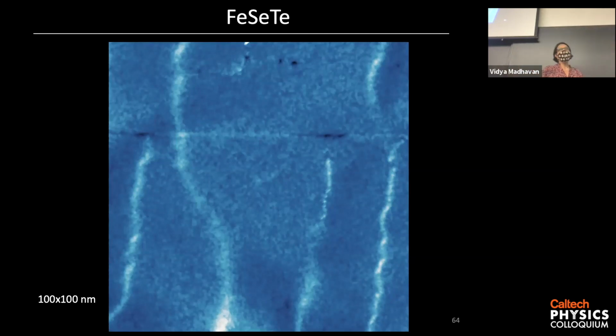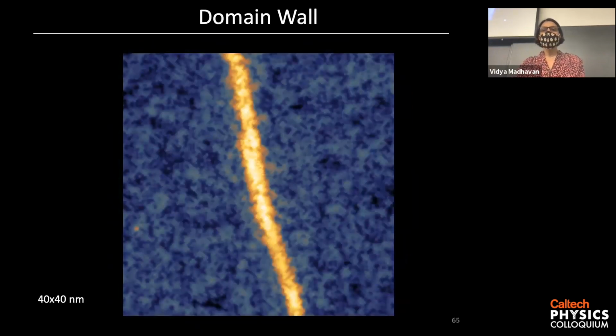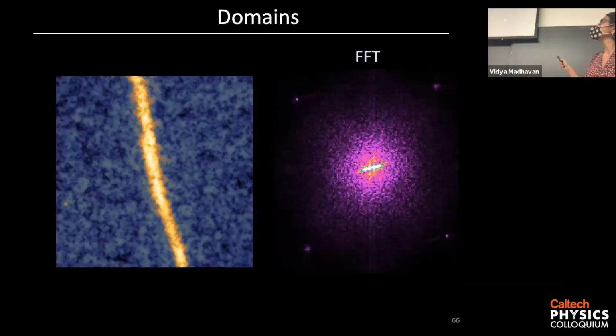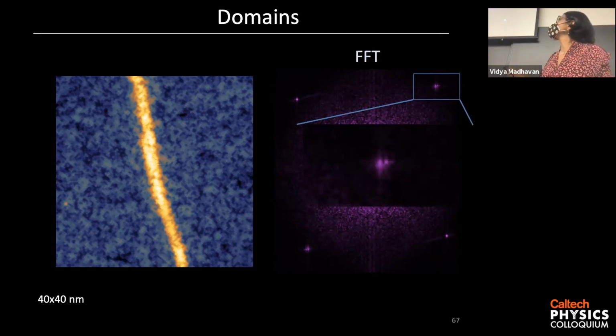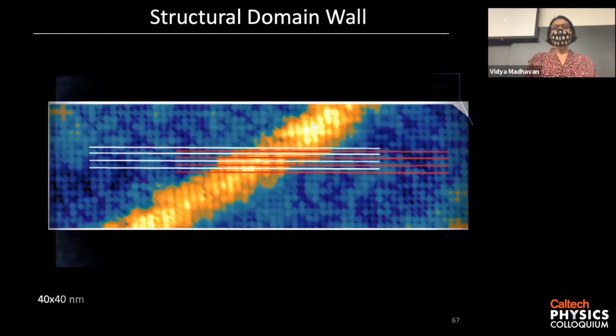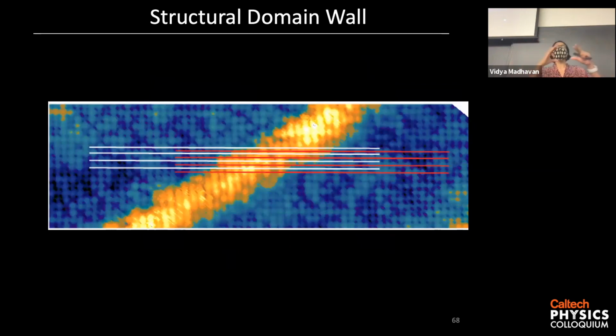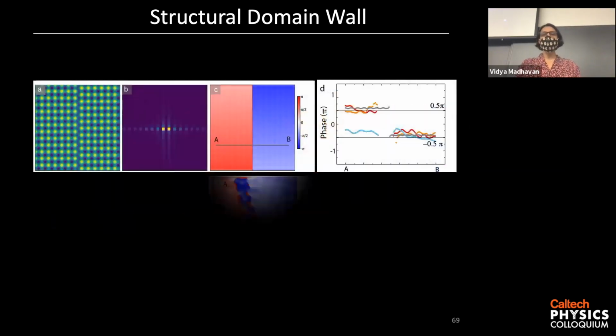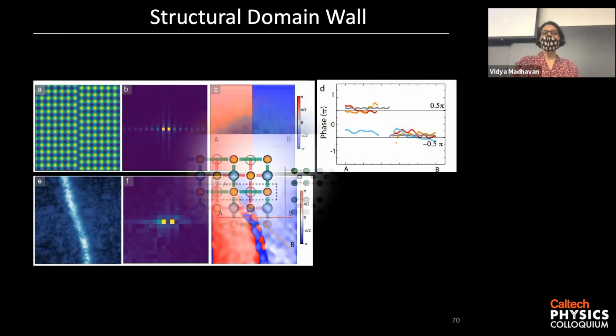In order to figure out if it's the right kind of domain wall, you have to zoom in, right? This is a zoomed in view. And you see atoms on this side, atoms on this side. You take a Fourier transform. What you notice is that one of the Fourier peaks, this one and this one, it's split into two. And that's a sign that you have a phase shift in the atoms between this side and this side. So you already know that there's a phase shift. So the question is, is there a pi phase shift? Sorry, what I mean by that is, are the atoms shifted by half a unit cell? And we can see that from topography. We can also see it by doing some Fourier analysis that I don't want to get into right now.